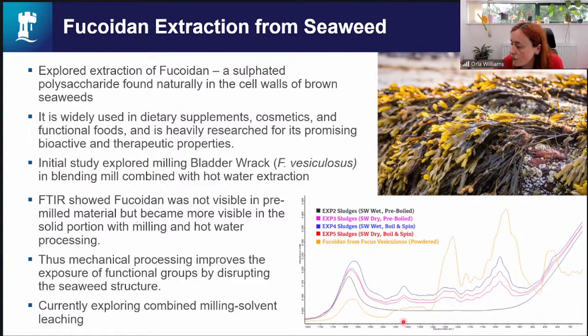So these are the FTIRs of the different processing steps. And we can see that you don't see it at the start, but then as you mill it, and we found that heating the water as you milled it made the fucoidan more visible than if you just heat it and then mill it. So the student did a lot of exploratory work and saw that we could start seeing the fucoidan was there, whereas it wasn't before.